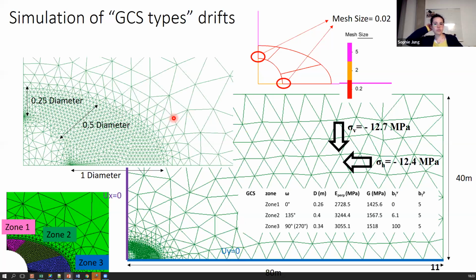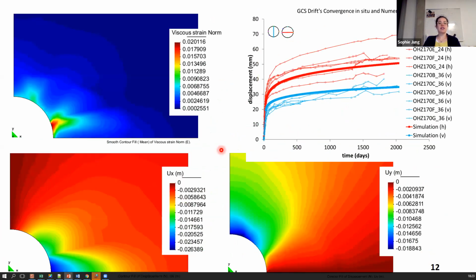So now I'm going to present very quickly the results on GCS types of drift, the drifts which present a horizontal fractured zone. We have simulated the convergence of the drift with an FEM code, with a model containing different zones of the different REVs presented before. So you have here 3 zones. I will go quickly. You can see that we can reproduce pretty well the convergences that are measured in situ.